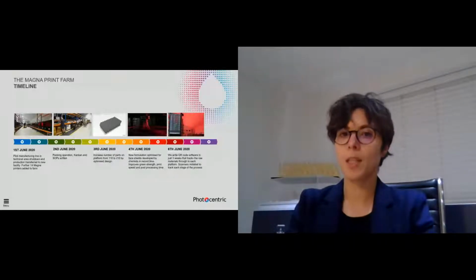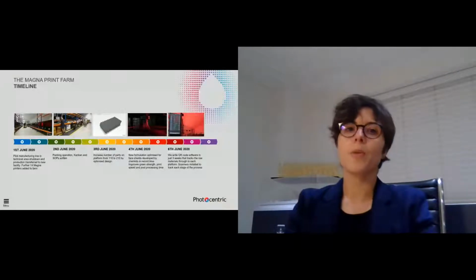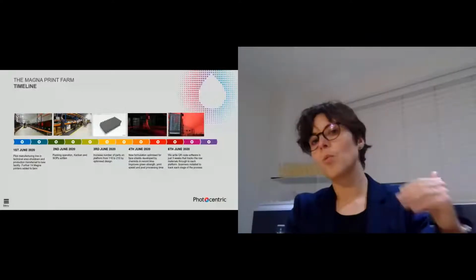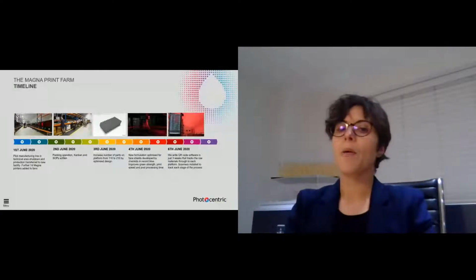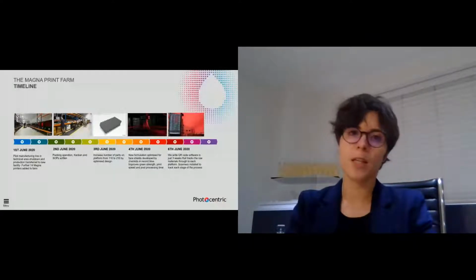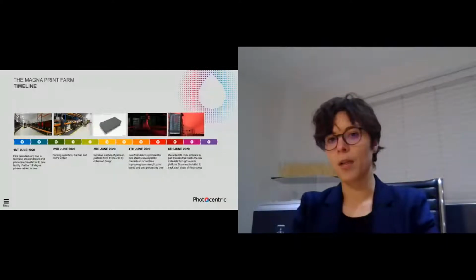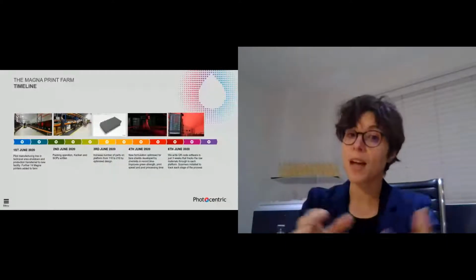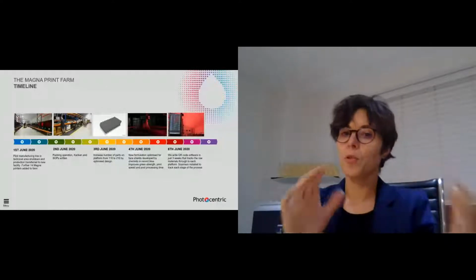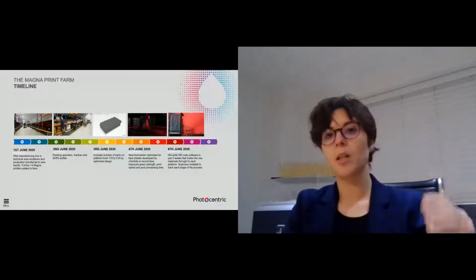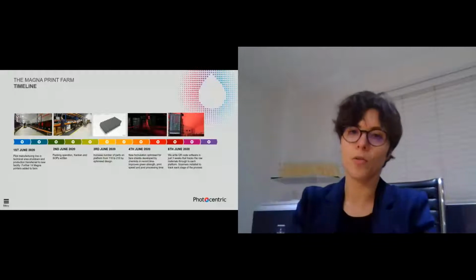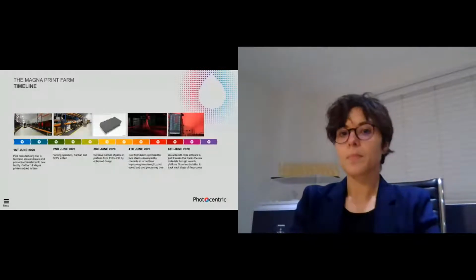Also, we worked on a new material. Classical 3D printing works by 3D printing 50 to 100 micron layers. Our new formulation was capable of printing 350 micron layers, so much faster, and with an improved green strength, so the parts were holding very well on the platform, reducing the amount of failures.